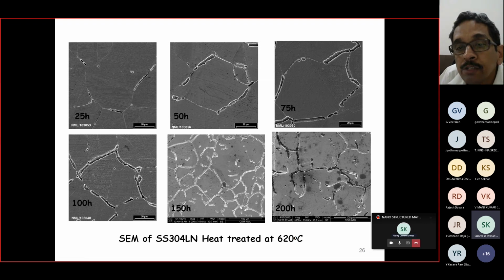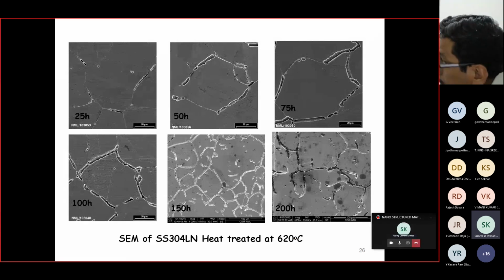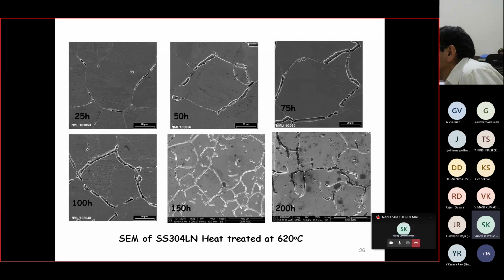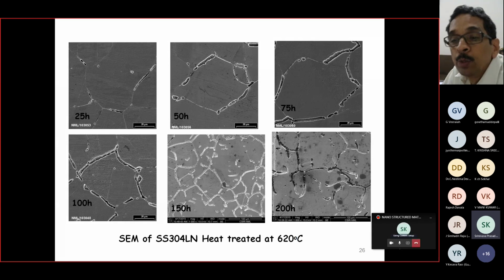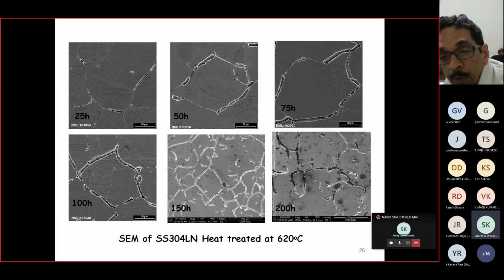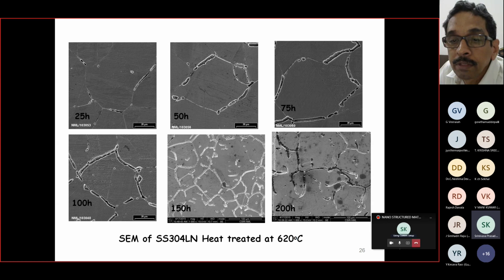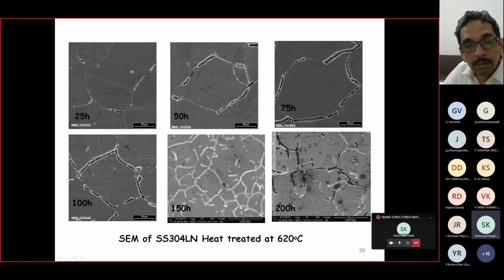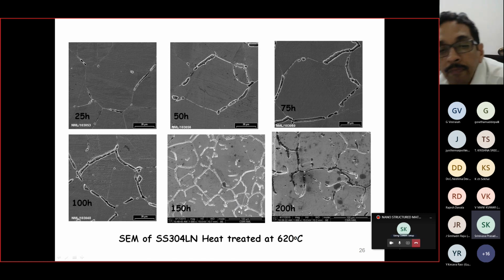the chromium carbide that is formed is very brittle in nature. When we are polishing these particular materials, this particular chromium carbide is removed. It is lifted off. Lift off has occurred. That means when I am doing an abrasive polishing, this has come out of the material, and it has created some sort of a crater. In English it is called a crater. Gutter laga form.